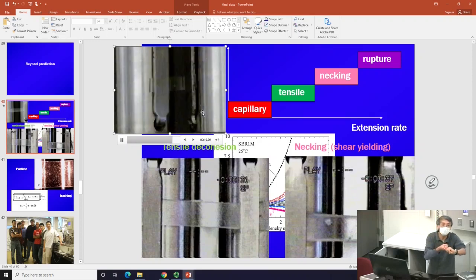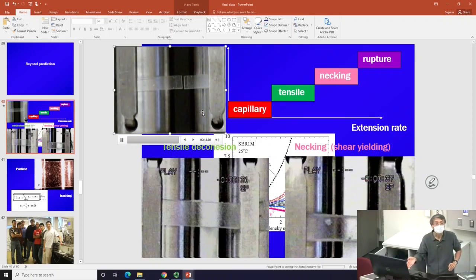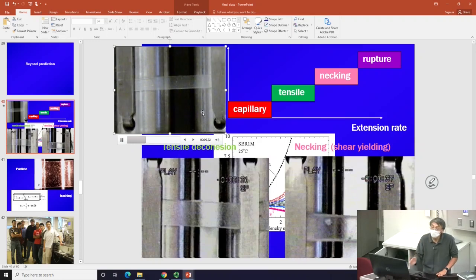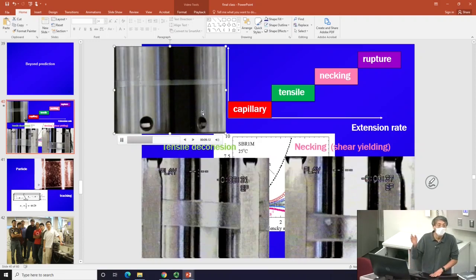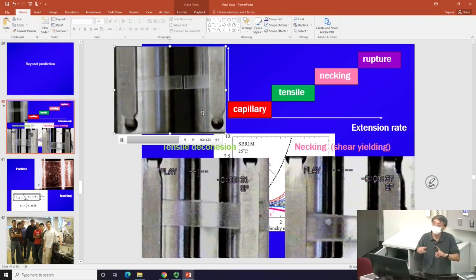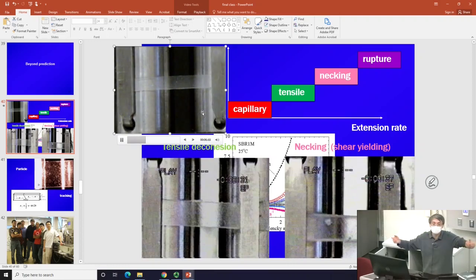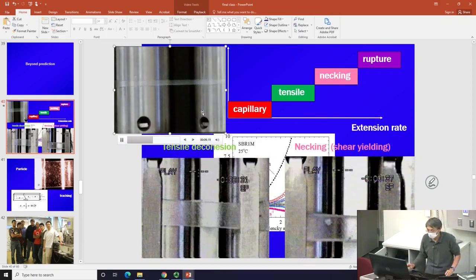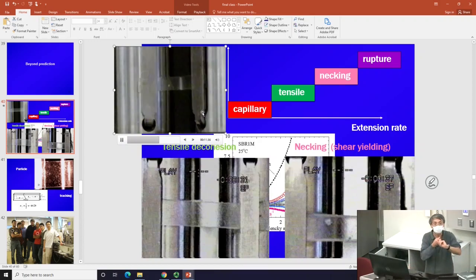And you can further claim, just based on this, that this indeed looks as if it's cross-linked. Therefore, you can further claim that this could only eventually happen by being triggered by chain scission. The chain has to break. In other words, the only way the system can escape further extension is for the chain to break. So the chain has to lock up.